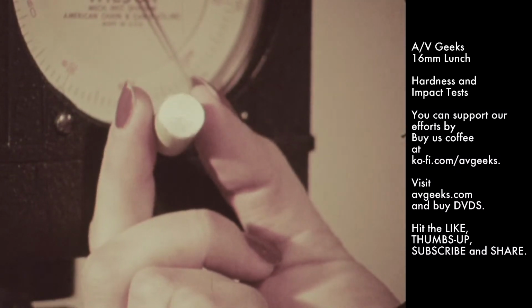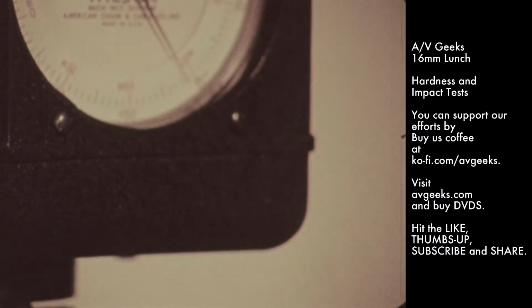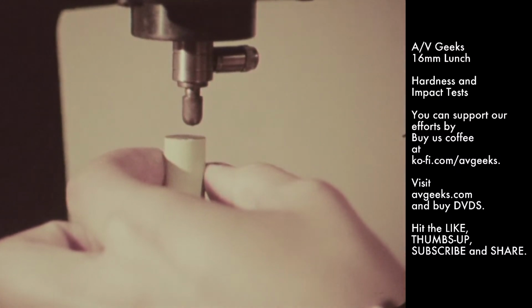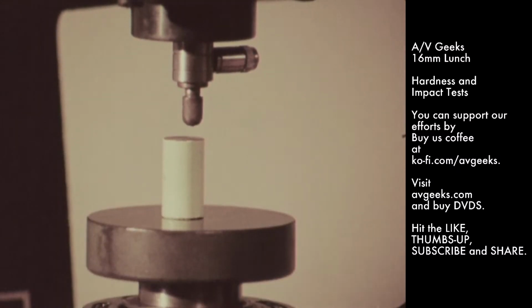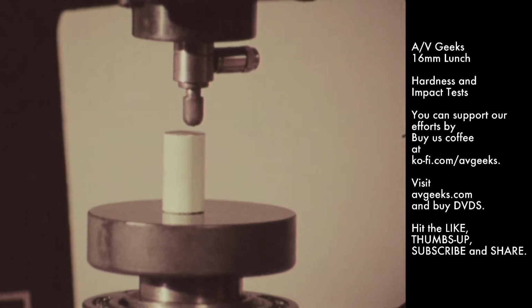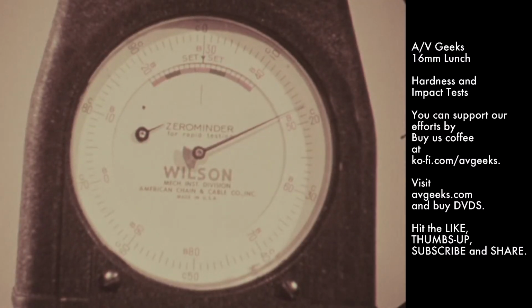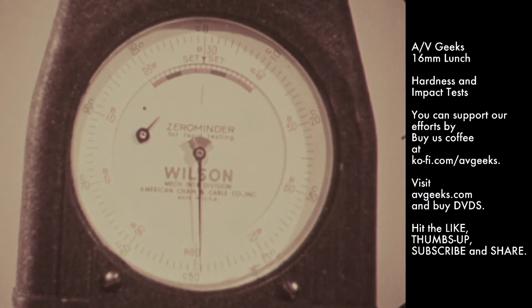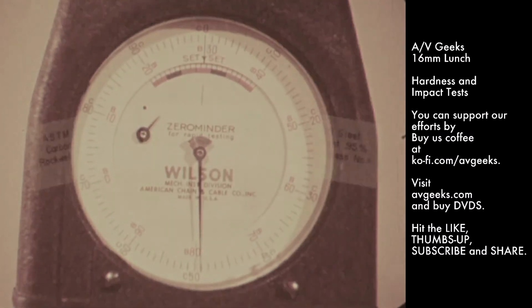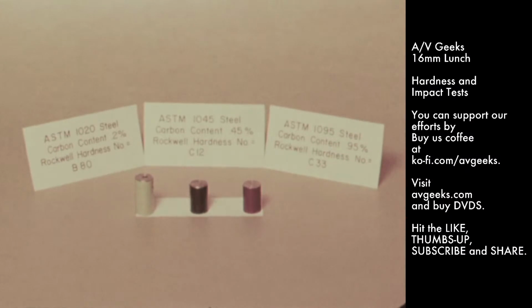The hardness of this ASTM 1020 steel specimen with a 0.2% carbon content will be read on the B scale. Its Rockwell hardness number is B80. We see from these tests that higher carbon content is associated with greater hardness. The tensile strength of these materials has also been observed to increase with carbon content.